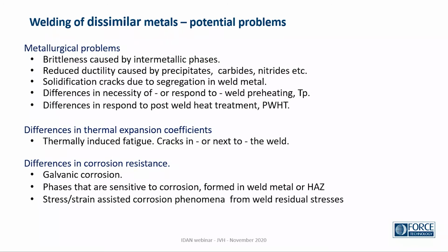We also see metallurgical problems, that is, problems with the metals in the melting zone or in the heat affected zone. Brittleness caused by intermetallic phases, that is, metals combining in a way that causes brittleness in the weld metal. We might have reduced ductility caused by precipitates. It's not strictly brittleness, but say in a bending test, there would be problems if we have too many precipitates. That might be carbides or nitrides.